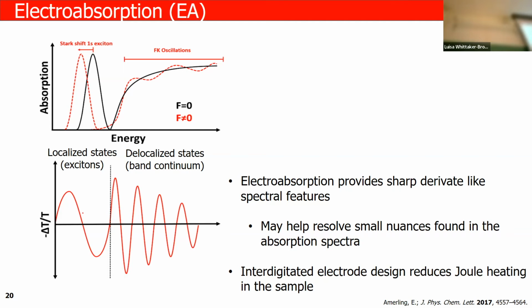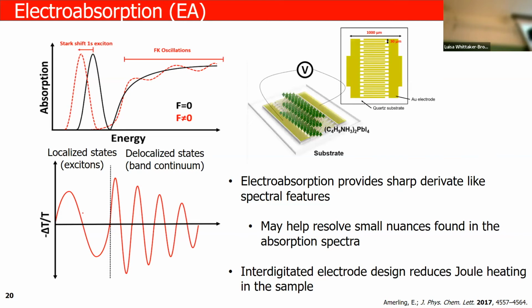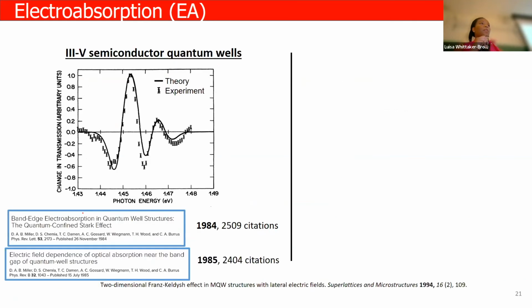But the thing is that if you actually make a diode-like structure, so out-of-plane structure, the film disappears in front of you because of the high field. So we actually had to change the arrangement of the film to have an interdigitated electrode to minimize Joule heating. Okay? So then when we actually end up making that sort of substrate, while we were making the substrate, we were digging the literature.